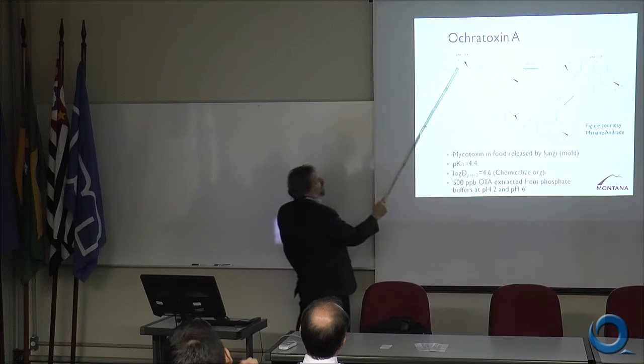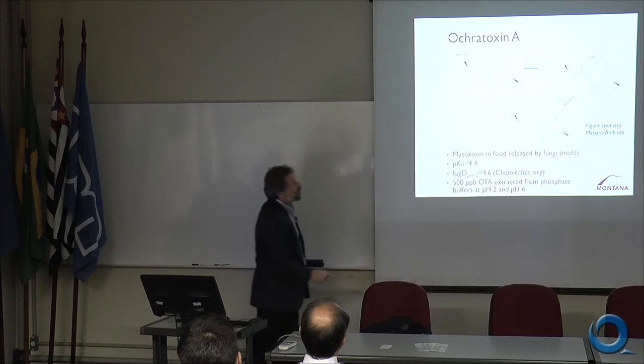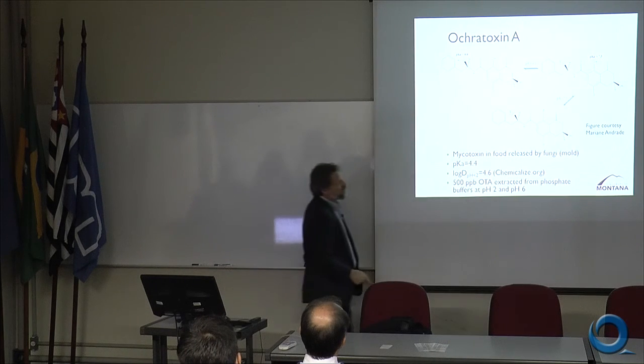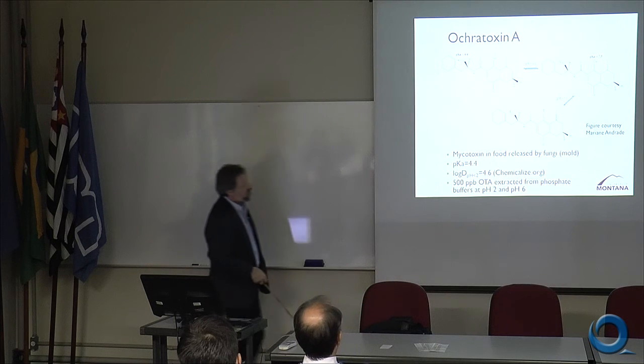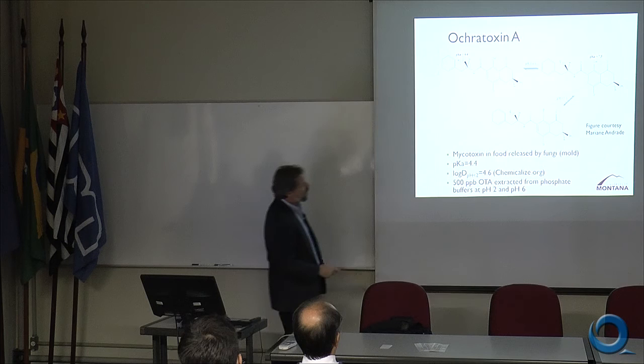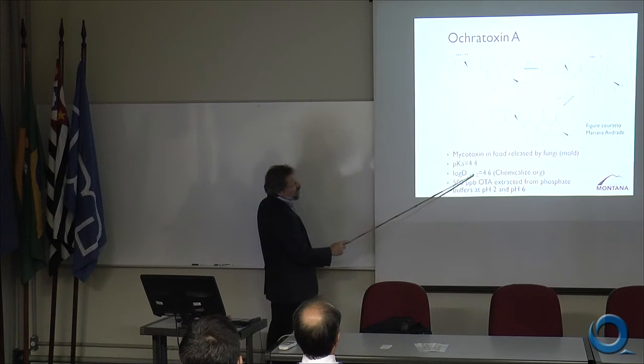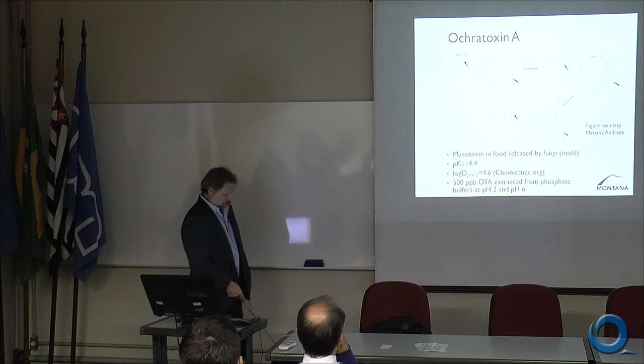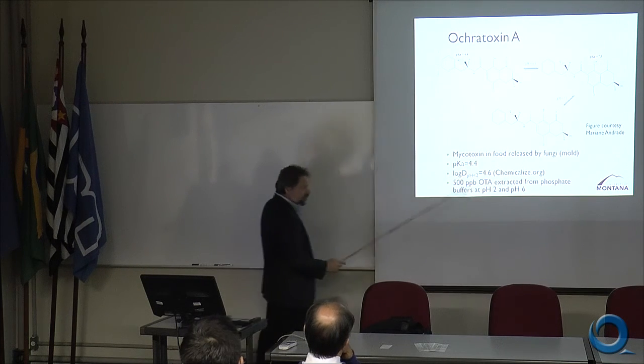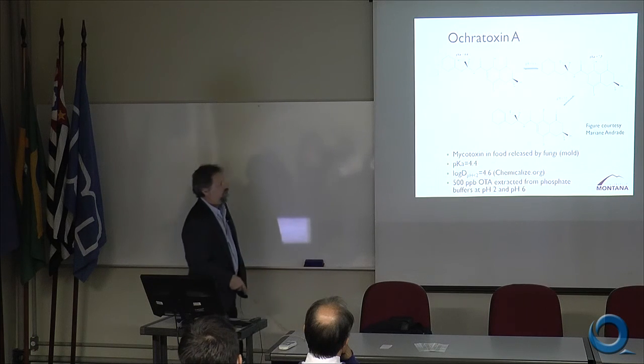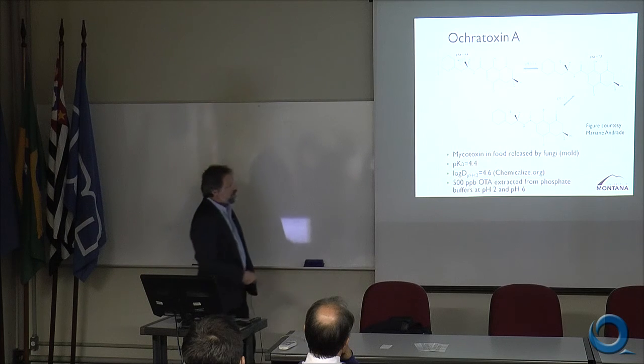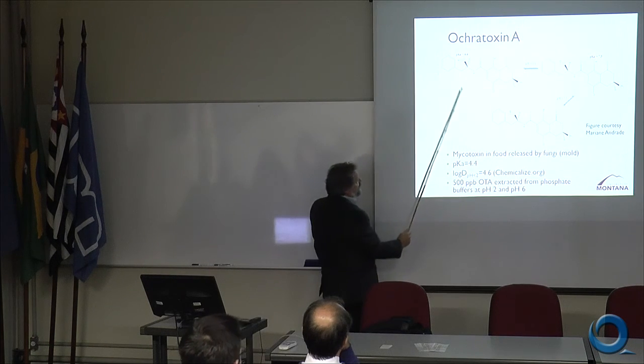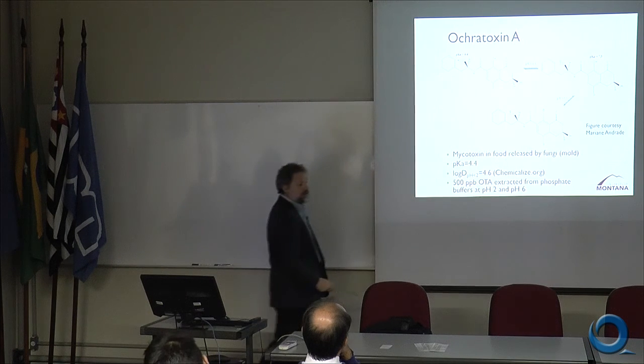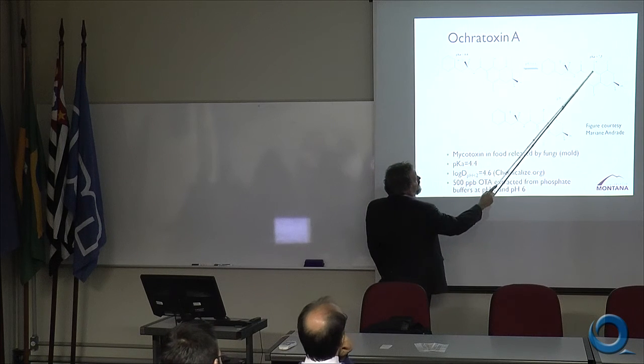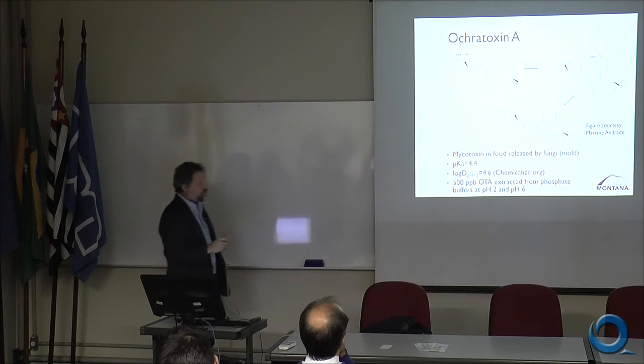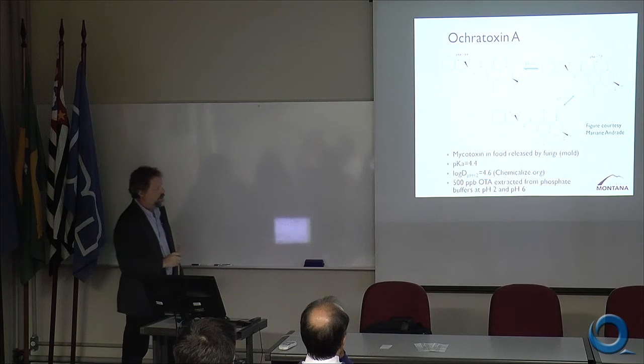So at low pH, well below 4.4, it should be in this non-ionic form. At higher pH, it should be in this anionic form. This figure I simply stole from a presentation that Mariani sent me. And it has a fairly large octanol water partition coefficient, a log partition coefficient of 4.6, so it's very hydrophobic. So what we expect is that at low pH, when it's hydrophobic, it will interact with the nanoparticles and be extracted. At intermediate pH, where it's anionic, it may actually interact even more strongly with the nanoparticles because of the ionic interactions that are available.